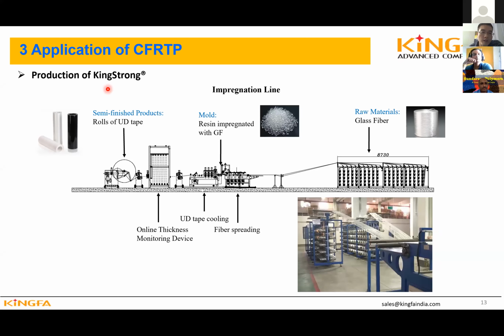This is what we call Kingfa. Here are some racks. We put all the glass fiber rolls in this place, and we introduce this fiber to the fiber spreading. And then here is a mold. The PP resin is melted and comes into the mold and contacts with the glass fiber. After the impregnation, the UD tape comes out from this mold, and then we do cooling and cutting. Then we finally get these UD tape rolls. So this is the first step to make the continuous fiber reinforced thermoplastic. During this production, all the glass fiber is continuous, so there's no breakage along the machine direction.